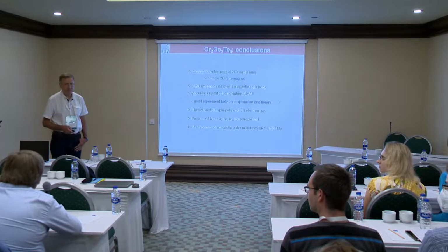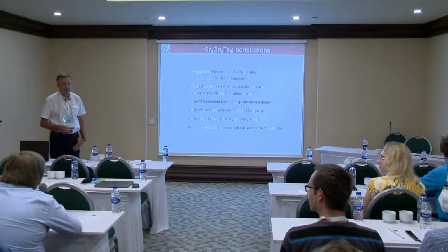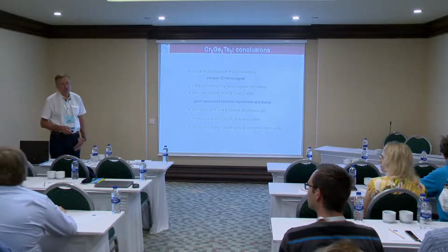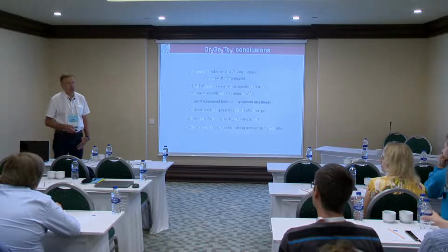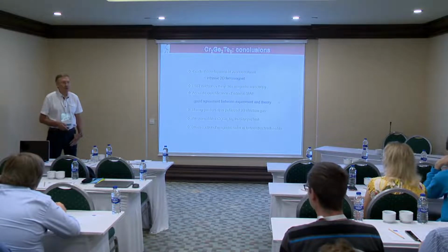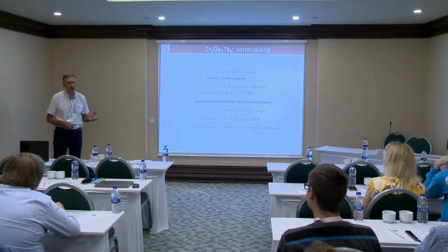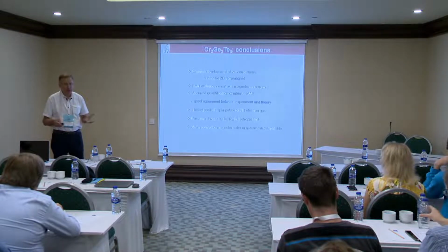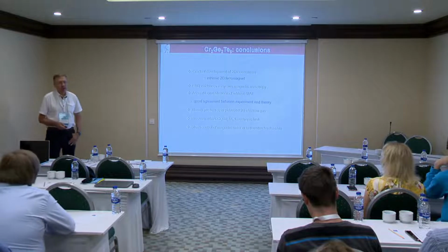Is it possible to say something about the exponent, and how far it is from the transition from an anisotropic two-dimensional ferromagnet to an isotropic ferromagnet? In terms of critical exponents, that would imply measurements. In the case of ESR spectroscopy, of course, this critical exponent should manifest, for instance, in the broadening of the ESR line, because the ESR line is a measure of the correlations. But unfortunately, in these particular experiments, we couldn't do that, because of technical complications.